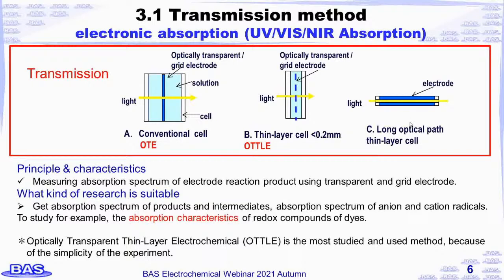By measuring the absorption spectrum of the electrode reaction product using a transparent or grid electrode, we can get the absorption spectrum of products and intermediates, and of anion and cation radicals. This transmission method was used to study, for example, the absorption characteristics of redox compounds of dyes. The optically transparent thin-layer electrode, OTTLE, is the most studied and used method because of the simplicity of the experiment. We will introduce some application examples using this method.